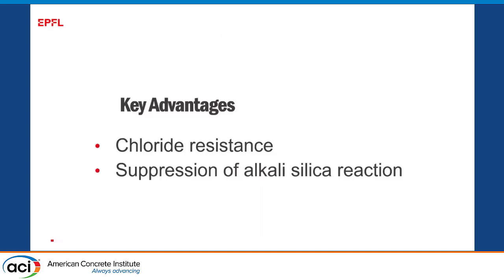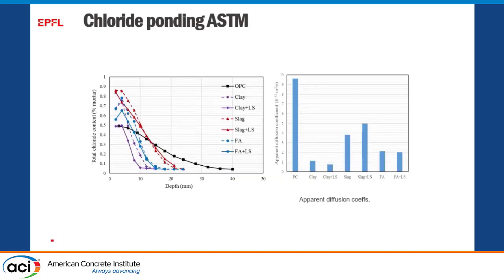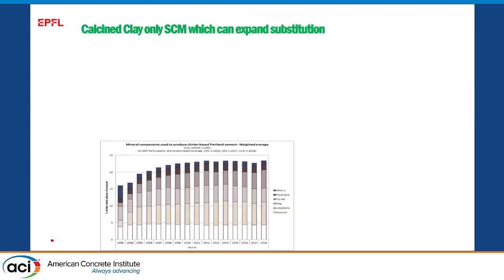So in terms of chloride resistance, it's much, much better. The black line is the reference Portland cement. The red are the mixtures with slag, which are better. The blue are the ones with fly ash, which are better still. But the purple ones at the left show you the dramatic reduction of chloride penetration you get with these materials. You have chloride diffusion coefficients about 10 times less than the Portland cement. Well, of course, if we use FRP rebar, we don't need to worry about that. But, if that's hopefully going to advance fast, in the meantime, this can be very good for marine environments.